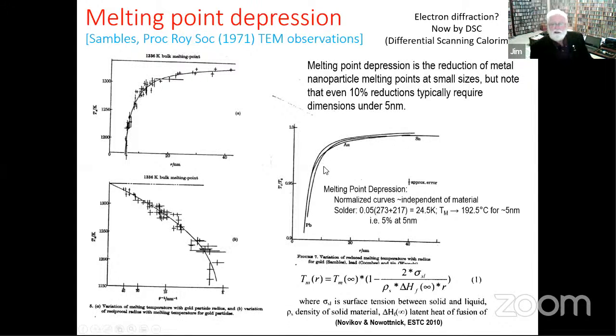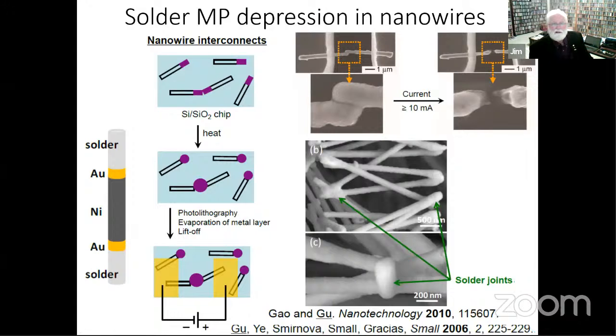These were observed visually. It should be possible to get the melting point accurately by electron diffraction, when the electron diffraction pattern disappears. But now this is usually done by differential scanning calorimetry. So for nanoparticles, for example, to try and lower the solder melting point is difficult in practice. It's not impossible. I was just thinking of a way that it could be done, but I don't know of anyone doing it. All of the nano solders that you see in the literature, actually we'll get onto a different subject for that.